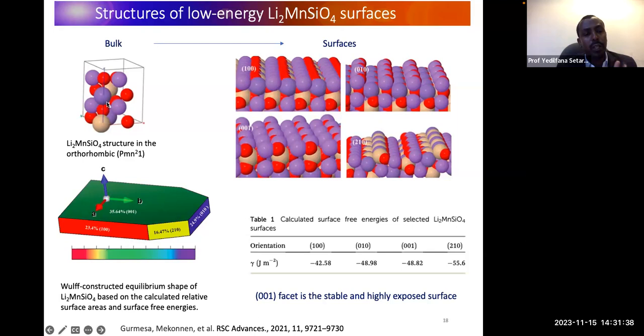So what we did is we have the initial bulk, then from the initial bulk, we cut different facets. We consider 100, 010, 001, 210, and calculate the surface energies, as you can see in this table. At the same time, we also compute the Wulff construction equilibrium shape of lithium manganese silicate based on the relative energies that we obtain from DFT plus U. What we get is that 001, as you can see here in the Wulff shape, is the highly exposed facet, with about 35.64% of the overall surface exposed. The dominant surface is 001, and the surface energy is also very good. So we identify 001 as a stable and highly exposed surface and make it ready for further analysis.